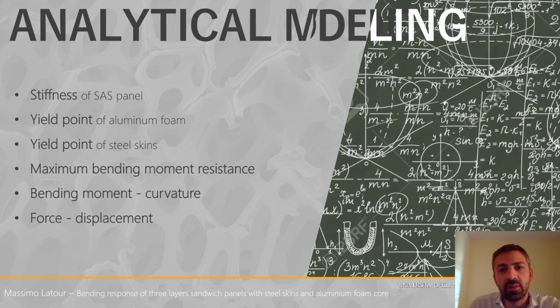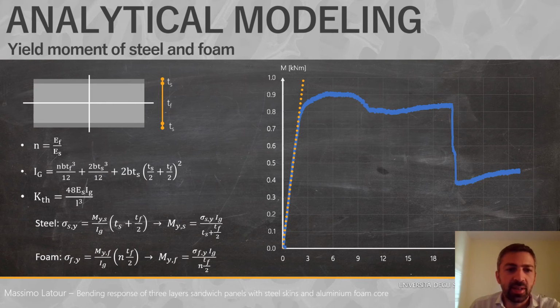In the paper, the accuracy of simple analytical formulas was also checked. In particular, we have checked the results of elastic and plastic analysis of the cross-section, checking the accuracy in terms of stiffness, prediction of the yield point, prediction of the maximum bending strength, and the bending moment curvature of the cross-section that was measured during the test. In particular, the typical formulas based on an elastic analysis of the cross-section were developed, checking that these formulas are very useful and very accurate in predicting the stiffness of the panels and also the yield point.